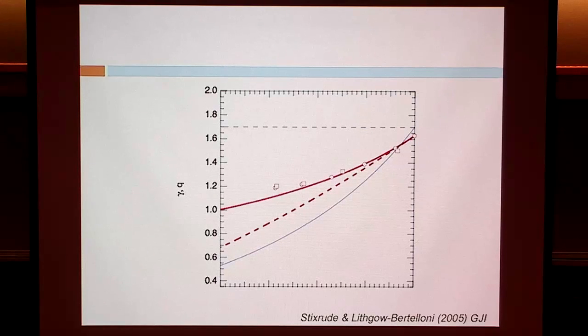So if you look at potassium, Mark Bukowinski looked at potassium, which is an alkali metal at low pressure, but as you compress it, the D states end up rising in energy less fast than the S states, and so potassium becomes a transition metal as you go up in pressure. And that's just one example. I'll show you a few more of changes in the electronic structure that can happen on the way towards this infinite pressure limit. Lots of interesting things can happen, and the Grüneisen parameter can go up and down and up and down. It doesn't necessarily smoothly tend towards this 2/3 infinite pressure limit.